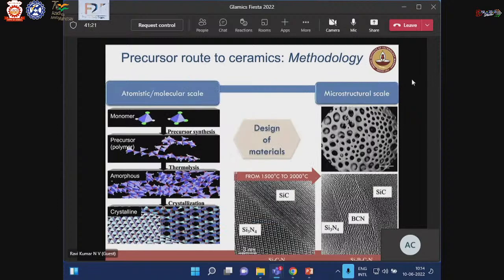Just to give you an idea of how we can do this, on the left hand side you see the schematic of the process, how we start with individual monomer units. On the right hand side, I show microstructures to give you an idea of how we control the microstructures. At the top, you see a microstructure which is highly porous. So we are able to control porosities to make sure that we can use it for specific functional applications. For example, we make highly porous ceramic materials for catalytic applications. On the other hand, below here, you can see high resolution transmission electron micrographs, where we show how materials can be made high temperature resistant.